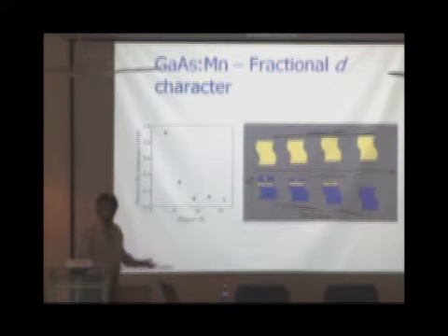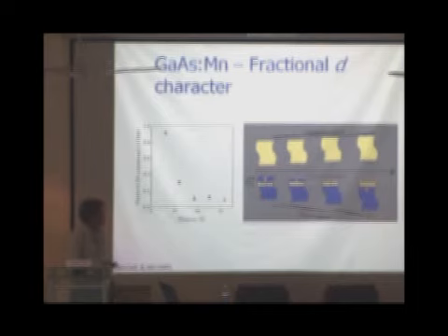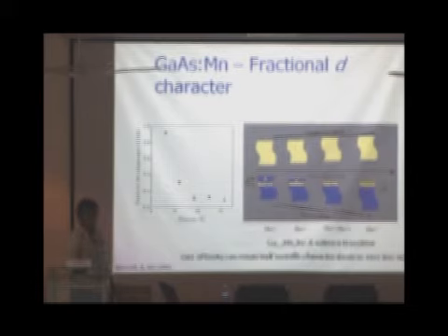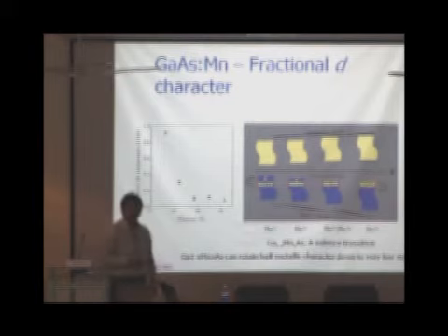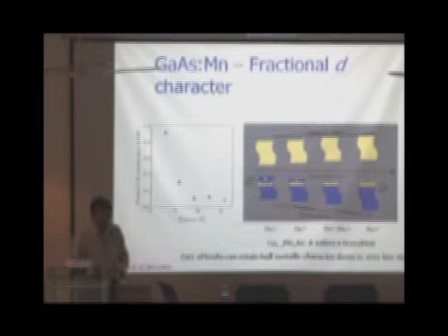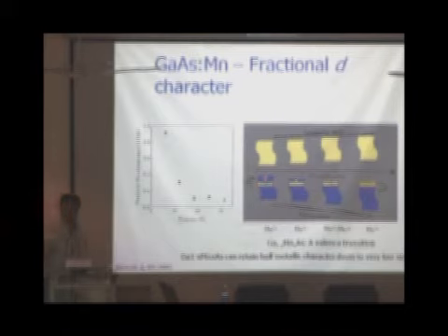And if you keep on further decreasing the size of these particles or increasing the band gap, the manganese level is going to come on top. Right? And then this hole is no longer going to lie on the valence band. It would like to float up. Right? And what would happen is some kind of a valence transition from manganese 2 plus to manganese 3 plus. So as good as about 2 nanometers, you don't have to worry, go down in size.